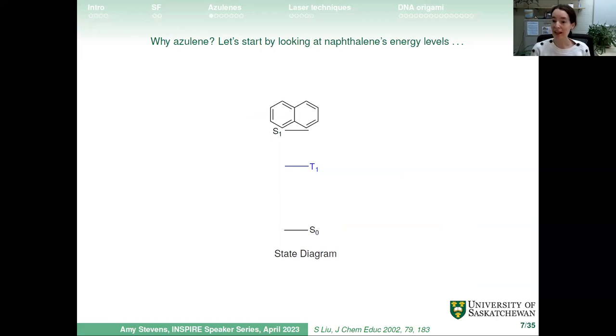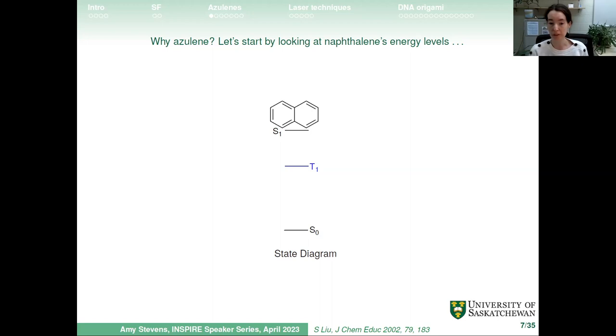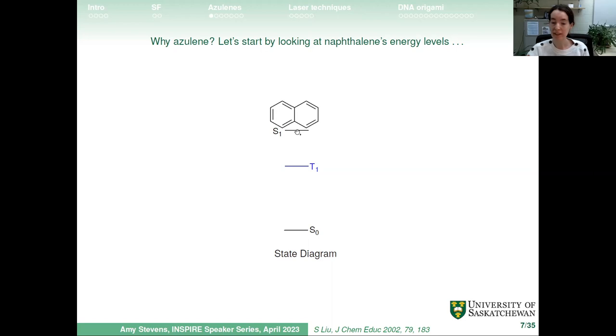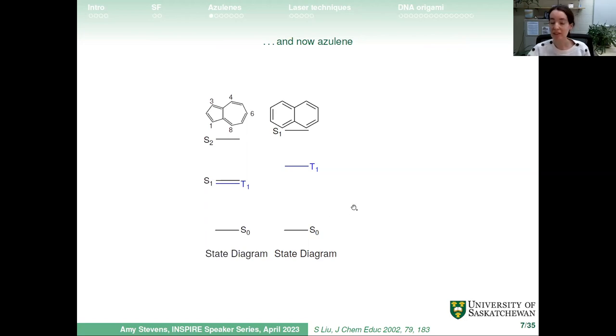We started looking at azulene — but why azulene specifically? There's only a small range of molecules that can undergo singlet fission, and we think azulene could be the next major class. Let's compare to naphthalene, its close isomer. Naphthalene has typical energy levels: ground state S0, first excited singlet S1, and a triplet T1 that isn't halfway between them. Azulene is quite strange — the energy gap between S1 and S0 is very small, while the gap between S2 and S1 is unusually large.